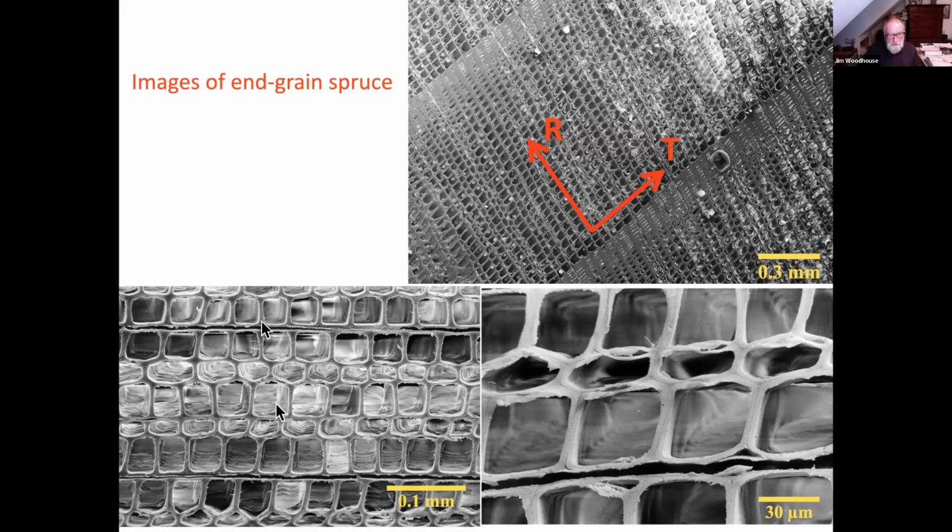If you think of squashing in that direction, bending the cell walls, it's easier to bend the ones in the middle. So the alignment in the radial direction makes that one a little stiffer than the cross direction, and that is the main factor, rather than the rays. If there was a higher density of rays, the rays also take you in the same direction.